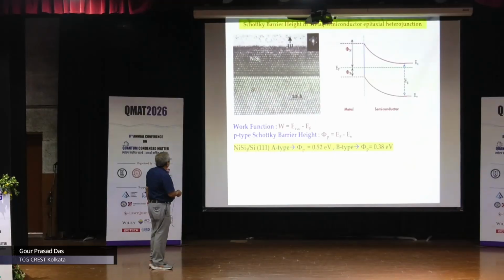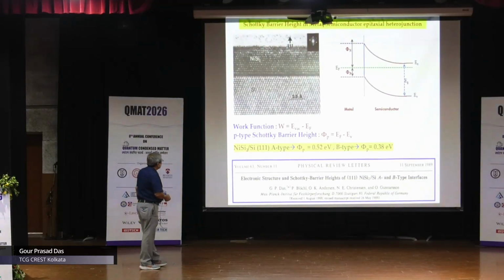Now, particularly, the system nickel disilicide on silicon was chosen by us long back. Here you can see the high resolution cross-sectional transmission electron microscopy, and look at the intimate interface. I mean, nickel disilicide ends and silicon begins, or silicon ends and nickel disilicide begins. There is hardly anything in between. It is called the intimate epitaxial interface, and this